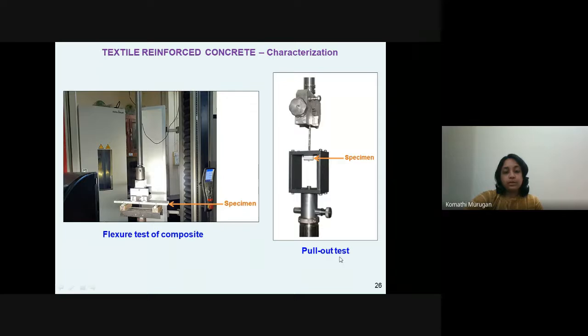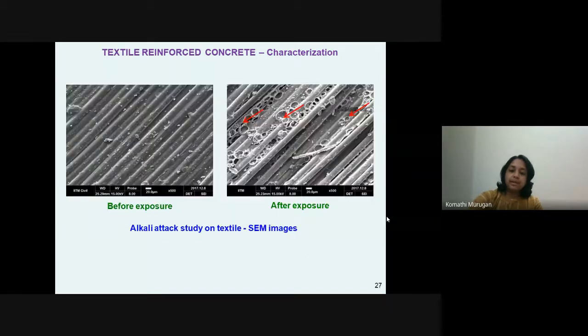Also, we do the pull-out test on these textiles, on the pull-out specimens. These are specific specimens where a single yarn is embedded inside the matrix. This is very similar to the pull-out test which we do with steel rebars embedded in concrete to understand the bond properties, how good the textiles are embedded in concrete and their bond characteristics. Again, these are for the modeling. So that is all about the mechanical characterization.